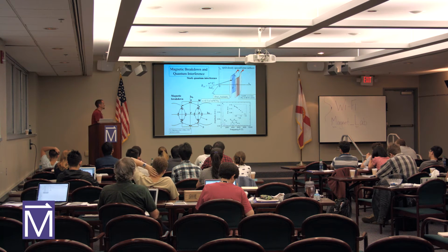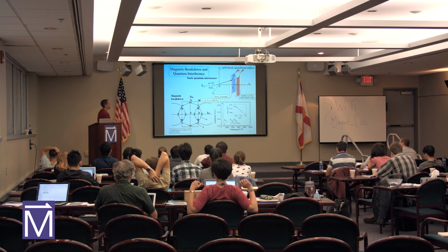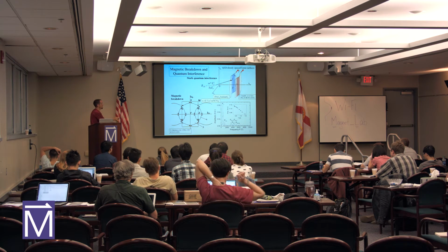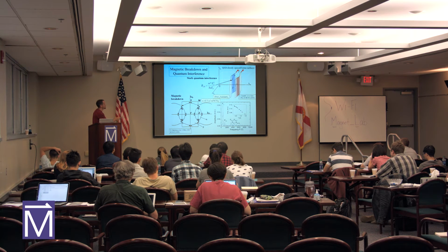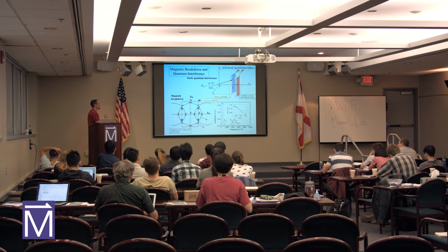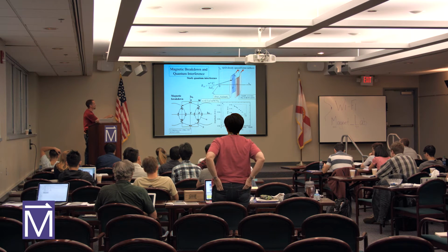Okay, some other oscillatory phenomena you might see in a high field measurement. Strange things that we occasionally see here. These are quasi one-dimensional Fermi surface sheets. They're both on one side of the Brillouin zone. So when carriers move along these sheets, they both move in the same direction, shown by the red arrows. Because these sheets are warped, they have points like C and E where the sheets are closer together. When you get the magnetic field to a strong enough point, interference happens between the carriers at these close points.